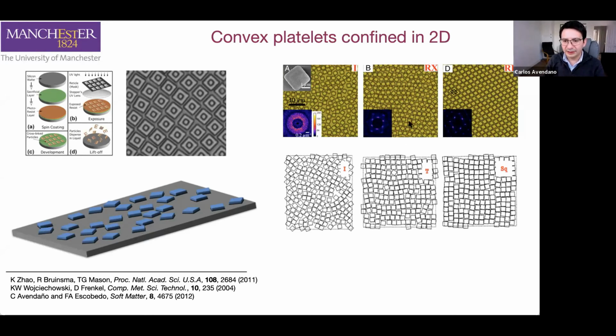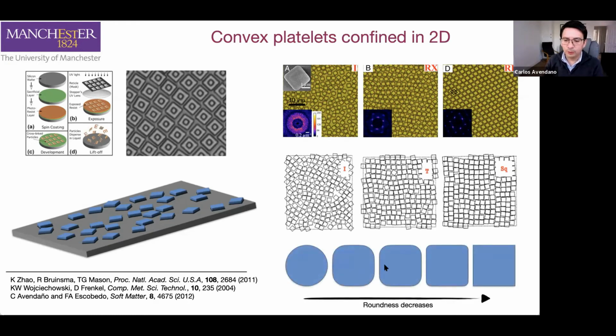So why the disagreement between the two systems, the experimental and the theoretical system? One possibility, which was explained in the paper by Thomas Mason, is that if you look carefully at these experimental particles, they are not completely sharp. There is a small degree of roundness in the corners. And the question is, is that enough to actually disrupt the phase behavior? So we decided to study that with a simple model in which we can change continuously between having a disk and a perfect square.